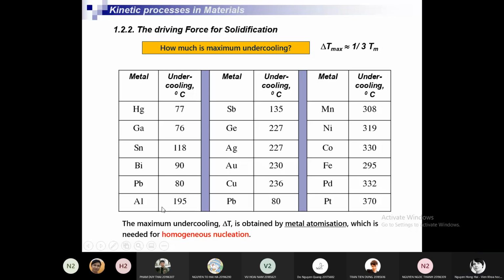See? For example, the equilibrium melting temperature of aluminum is 660 degrees. And if you can reach this undercooling, it means that at a very low temperature, about 465 degrees, aluminum is still in the liquid state. Aluminum is still liquid, not solid, if you can obtain this undercooling.